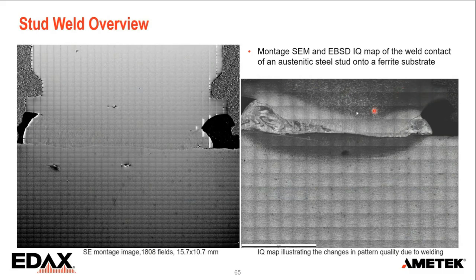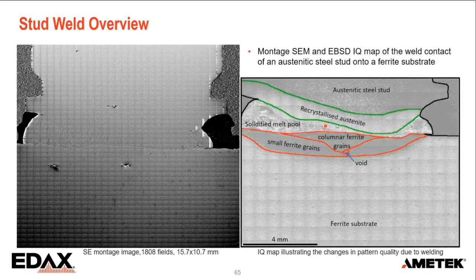I'm not going to talk about that, but close to the interface, we have this bright band. That's recrystallized austenite. Then we have this zone with these little swirls in dark. That is the area that was molten. And down here, we have the ferritic structure where the pattern quality, which was quite good initially, has deteriorated a lot. So what exactly is happening there? Just to illustrate that, I've just made a little drawing. Here we have a recrystallized austenite, the melt pool, and in this ferrite area we have two zones. One is fine-grained ferrite, and this is a columnar ferrite.